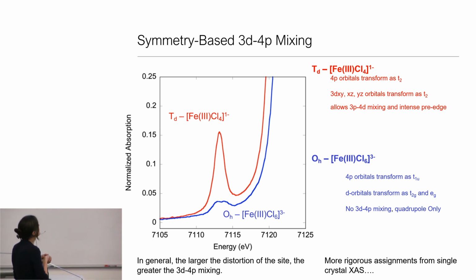But what you nicely see experimentally when we go to a tetrahedral ferric tetrachloride complex, from group theory, we see that, of course, the 4p orbitals now transform as T2, and we also have a triply degenerate set of t2 orbitals that transform as XY, XZ, and YZ. And so this gives you a means, by group theory, for p and d to mix. It gives you a mechanism to get dipole allowed character, which will give you much more intensity, about 100 times more intensity than quadrupole. So you only need a small amount of 4p to get this, and it's immediately reporting on large differences in site symmetry. Okay?